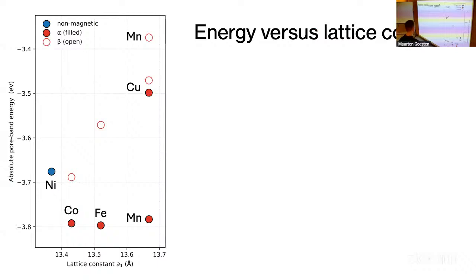When we look at the nitrogen MOFs, the ones where NH is the binding site, these are some preliminary results. What we do then is calculate, using many Slater functions, the absolute energy using AMS to get an ionization potential estimate. And then we look at the absolute energy of that pore band. Most of these MOFs are magnetic. Currently we are finishing calculations for platinum and palladium just to add two non-magnetic systems to it.